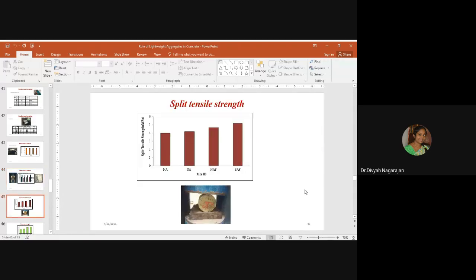Now coming to the split tensile strength, the sintered fly ash aggregates, as I said, have better tensile properties when compared to other lightweight aggregates. So there is not much difference in the split tensile strength when compared to the normal aggregate, but when fiber is added, the split tensile strength increased.